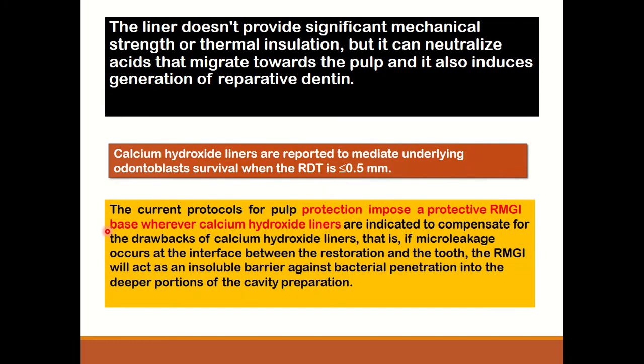These liners do not provide significant mechanical strength or thermal insulation, but they can neutralize acid that migrates towards the pulp and also generate reparative dentine formation. Calcium hydroxide liners are reported to mediate underlying odontoblast survival when the remaining dentine thickness is less than 0.5 mm.